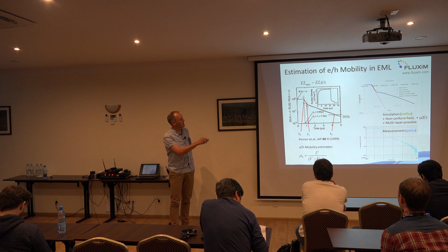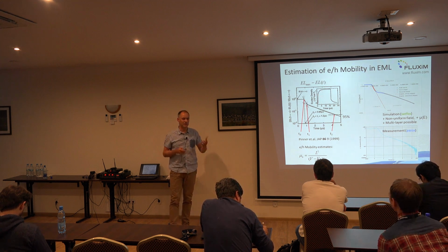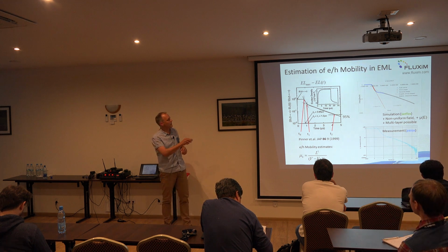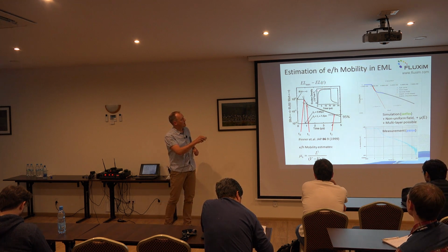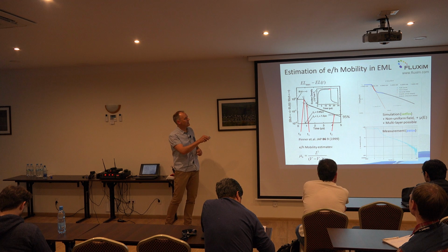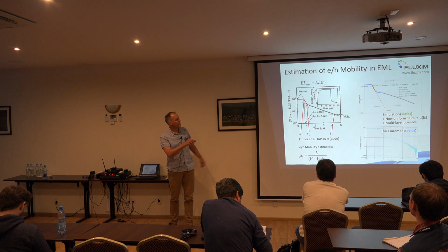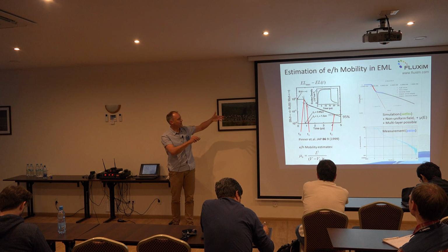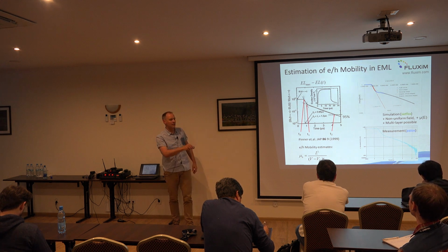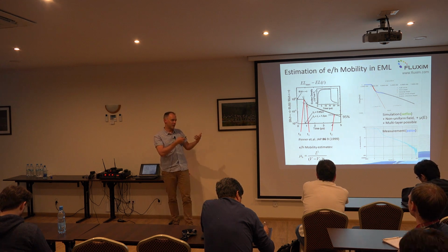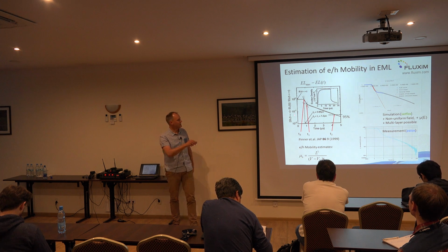And you see also there that turn-on has a steep and a kind of slow component, but you can only see them if you take the maximum EL light minus the signal, so to have data that looks like a decay. So the same turn-on data is plotted differently such that it looks like a decay, and then you can extract the 2 exponential components of the dynamics.